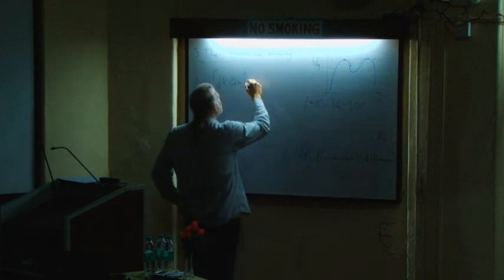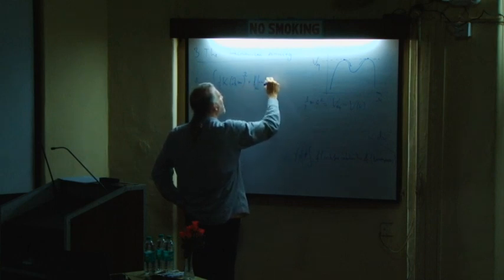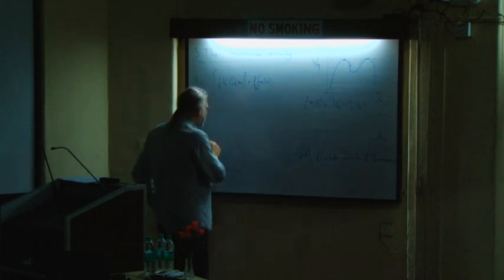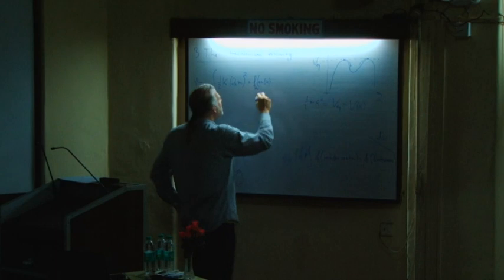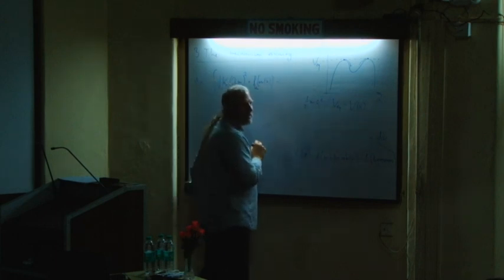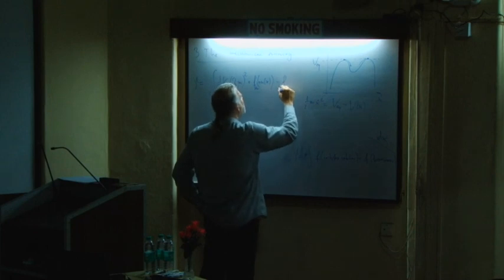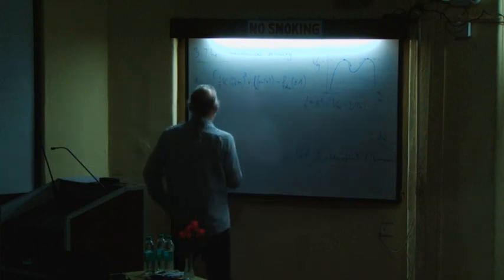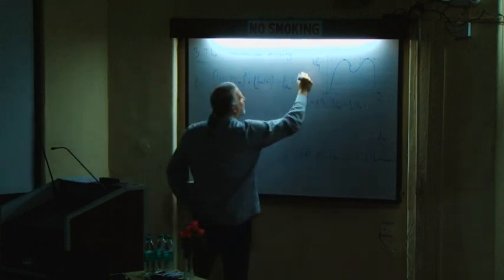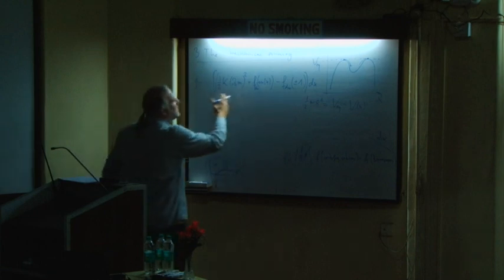For the potential term, it's different, because here I have f double well of m of x. That's the potential in my interface solution when I have to go over the hill. And I need to subtract from this the value at equilibrium. So this is f_dw at plus or minus 1, which corresponds to my equilibrium states. Okay? And I need to integrate all of this with respect to dx. So this is an exact relation for the surface tension.